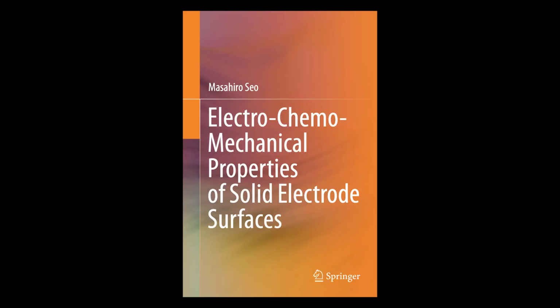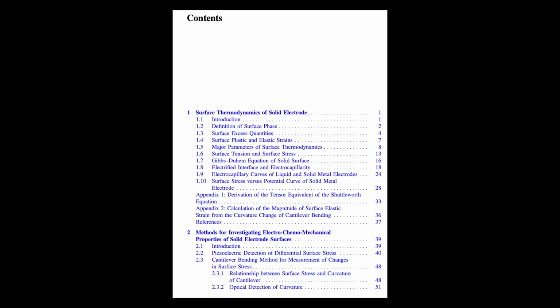Absolutely. Let's take another specific example. Iodine adsorption on gold (111). Experiments show a nice linear relationship between the change in surface stress and the surface elastic strain caused by that layer of iodine atoms sticking on. Okay. And this linear relationship actually lets us estimate mechanical properties of the adsorbed layer itself, like its two-dimensional elastic modulus. Whoa, hang on. So we're not just seeing a change in the gold stress, but we can use that change to figure out how stretchy or stiff the iodine layer is. That's powerful. It is indeed. It gives you a window into the mechanics of these ultra-thin layers.